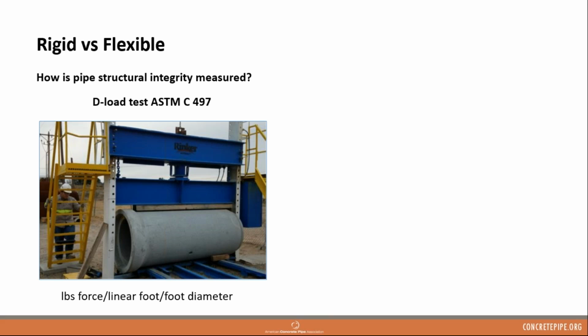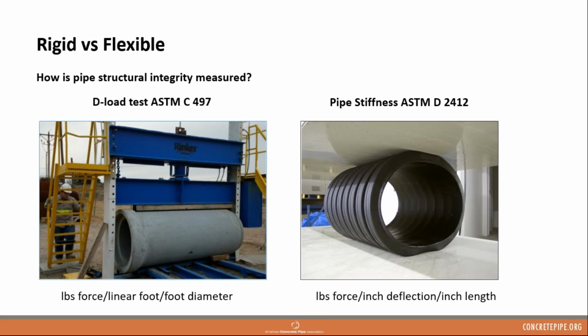For a flexible pipe, the available test is called the parallel plate test. As you can see from the picture on the right, the test piece is placed between two plates and subject to a load. The load is applied until the pipe is deflected a certain percentage from round, and then this result is recorded and expressed in pounds force per inch deflection per inch length. So now knowing what we know about a flexible system strength, we can tell that this value isn't particularly helpful in trying to determine how much load the pipe will be able to withstand once installed, because it's the soil that provides the strength in the system.